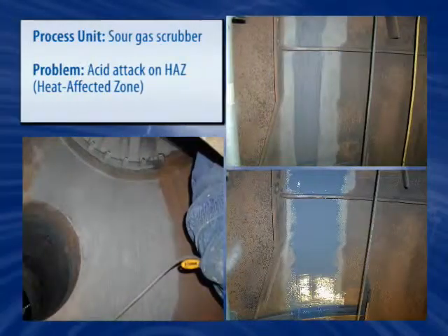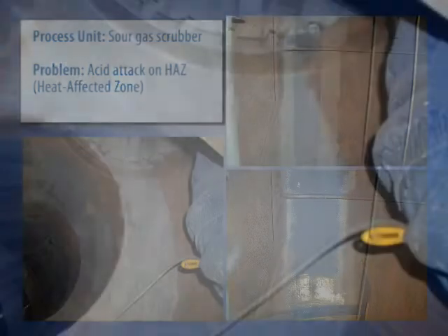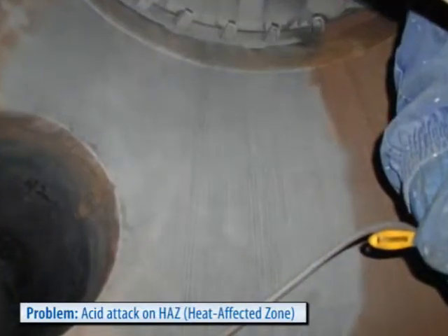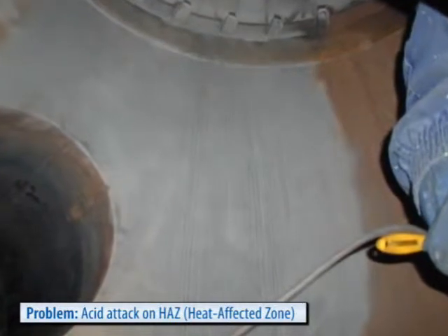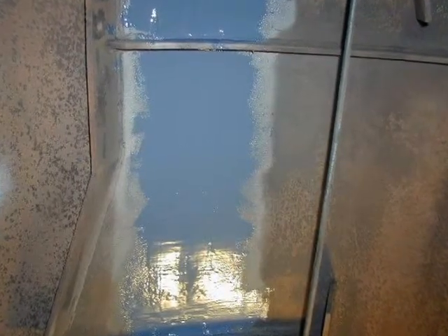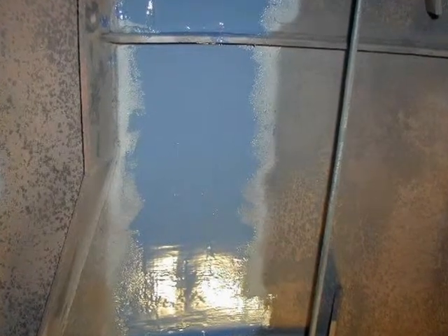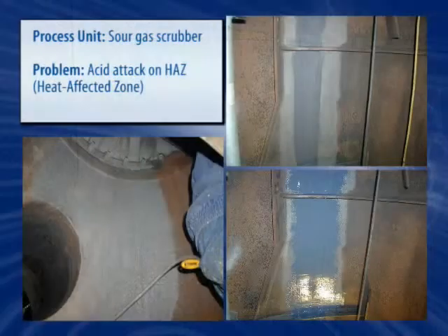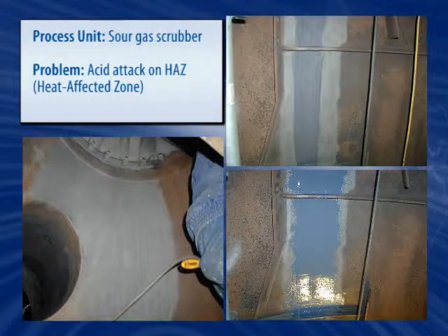Acidic byproducts, especially in gas scrubbers, pose a challenge to any coating system. Over 45 feet of weld seams were protected with a Belzona coating system capable of withstanding the high temperatures and aggressive chemical environments typically seen. This application has allowed the tower to remain in uninterrupted operation for over 3 years.